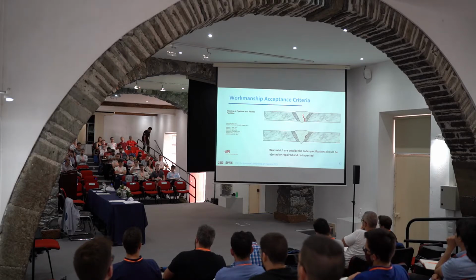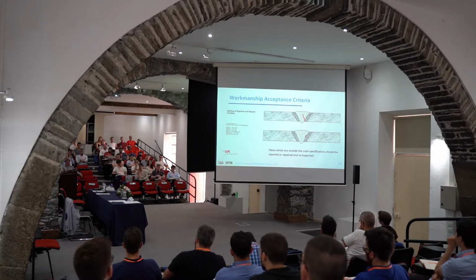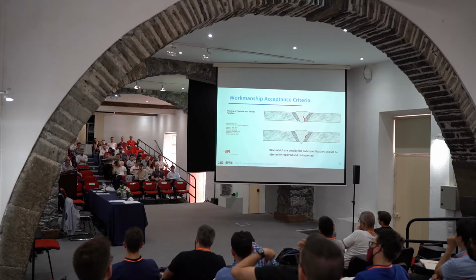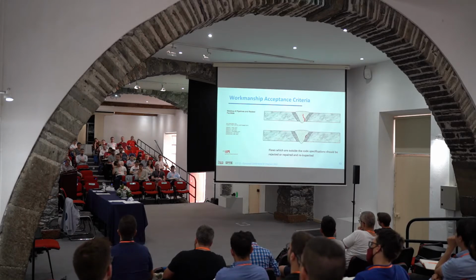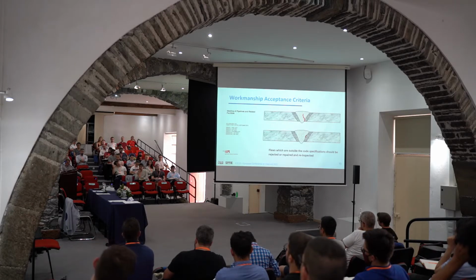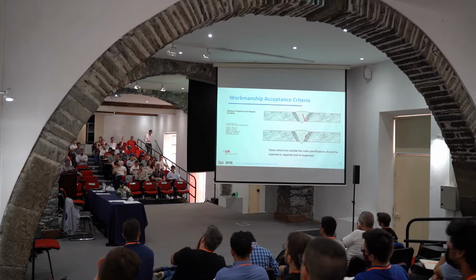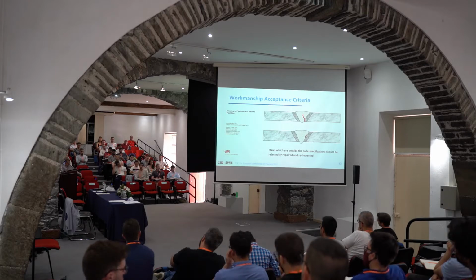okay, by the way, there's a difference between a crack and a flaw. A flaw, of course, can be a crack, but for example, porosities, some volumetric imperfections that may arise during the inspection of the welding, can also be categorized as flaws. So they are volumetric. For example, they are round. So actually, I am assuming that everybody here took a course on fracture mechanics. So you know the stress fields, linear elastic fracture mechanics, HRR stress fields, J integral. So you need a sharp crack to derive your crack tip stress fields. When the flaw is blunted, so it's round, there is, let's say, a finite radius. Strictly speaking, we don't call this a crack. But for the workmanship acceptance criteria, they are flaws.